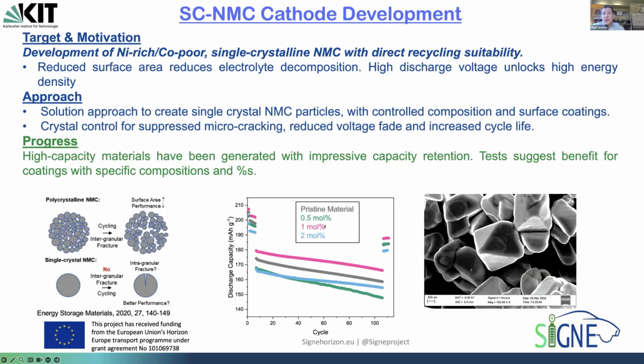What you see here is these are just kind of indicative values. So you have a pristine material here in gray, and they looked at different degrees of coating on those active materials. And what they found in a lot of cases is that there's almost a sweet spot in terms of the coating amount that you have. So in this case, it was this pink component here where they were able to find the right balance between coating thickness and cycling stability.